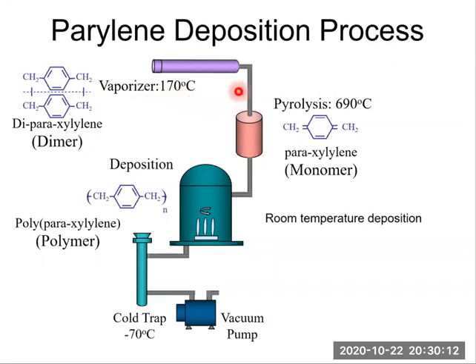And those dimers are broken down, split into monomers at 690 Celsius, a very high temperature, 690. This is called a pyrolysis process. It's a thermal breakdown process. So we obtain monomers. Then these monomers enter this deposition chamber and